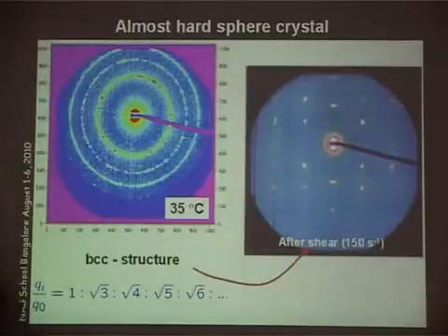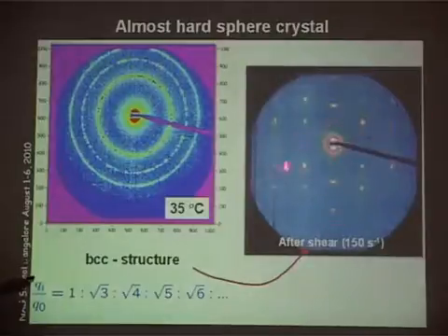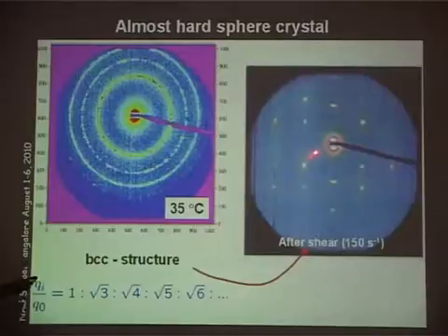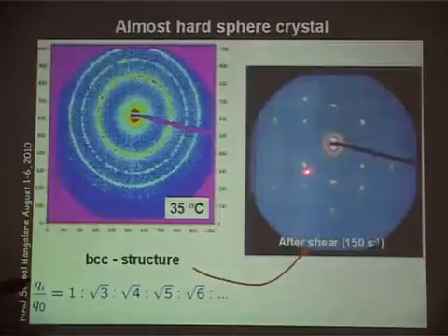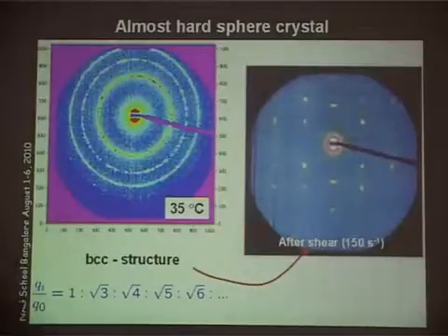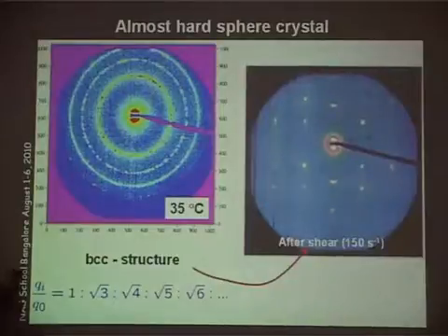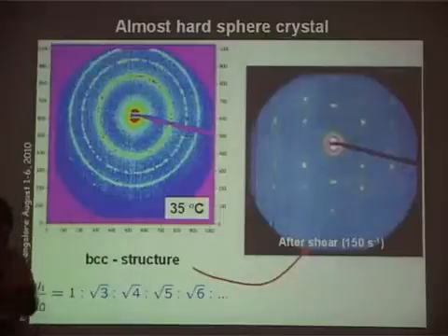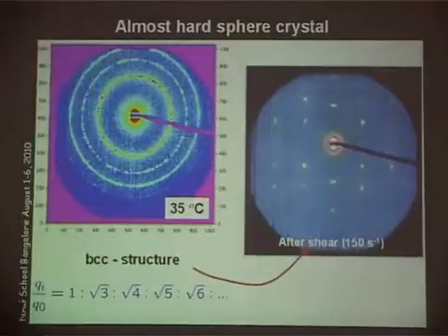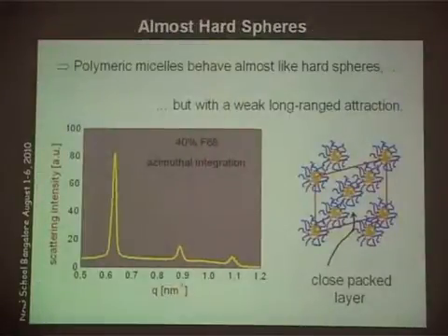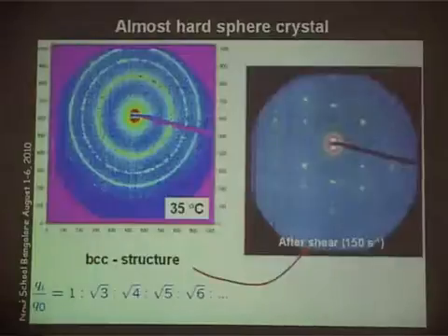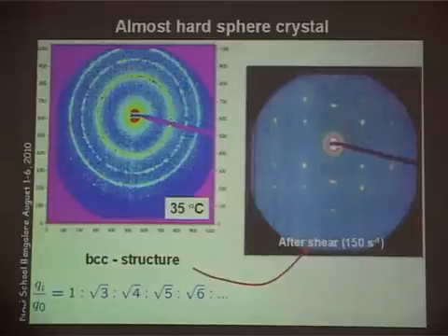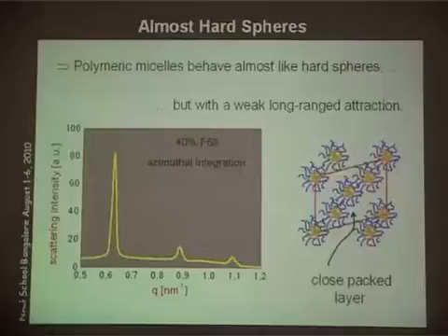But when you measure the elastic property, the elastic part of the complex shear modulus is half of this. So the well-ordered crystal is softer than the polycrystalline sample, because there you have lots of grains, and it's harder to shear those grains. They stiffen up the system. That's how we analyze it. With these spectra, you can azimuthally integrate them, and you get this picture and my peaks, and this is a BCC, just a way of showing how the BCC crystal looks like.